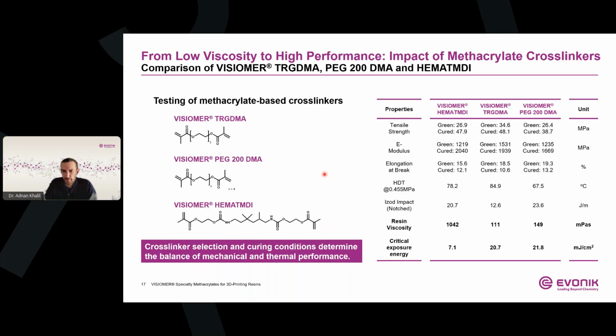This slide highlights an important aspect of the resin design, that the crosslinkers influence far more than just the mechanical properties. Looking first at the viscosity, you can see that the TRGDMA and the PEG 200 DMA result in much less viscous material, which can provide an advantage in the processing and make them potentially attractive for highly filled formulations or applications where a really good flow behavior is necessary. However, when we evaluate the properties of the cured material, the picture becomes a little bit more differentiated.